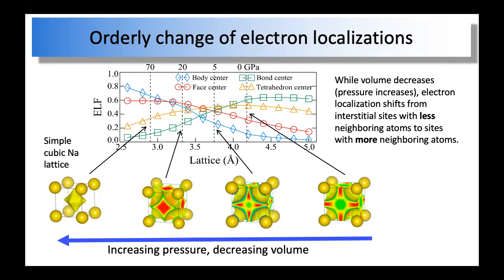But if you compress that, then the general trend is that the electron localization, at a larger lattice constant, is always localized at a position that has fewer neighboring atoms, right? So for example, at a larger lattice constant, it is localized here, and it has only 2 neighboring sodium atoms. But while you compress that, the maximum will move to the face center, which has 4 neighboring sodium atoms. And if you further compress that, it will eventually move to the body center, which has 8 neighboring sodium atoms, right?